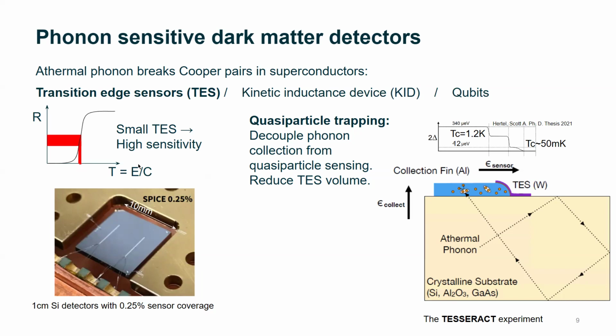And of course, for energy injection, the energy translates to temperature by dividing the energy by the heat capacity. The heat capacity is proportional first to the critical temperature of your superconductor, and also proportional to the total volume of your superconductor. So that means if you can reduce the TES volume, you can gain a lot on this sensitivity and also gain a lot on this energy resolution. So that's why here, this is our state-of-art device on a silicon chip, and we only have 0.25% instrumented area on top of this small silicon chip. Yeah, you can see these small dots. These are the individual TESs. The reason is because we want to reduce the heat capacity.